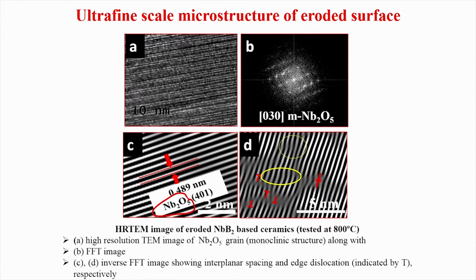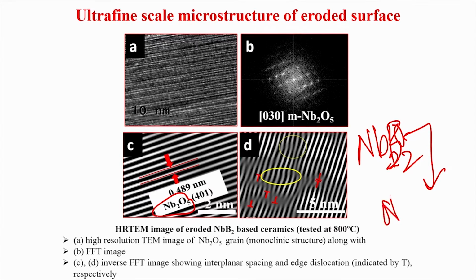Now, this niobium oxide formation is so low that one cannot record it using X-ray diffraction pattern, because their intensity or their amount is much less than what can be detected using X-ray diffraction analysis. But here what we can see is that the selected area diffraction pattern clearly shows that Nb2O5 has formed, and Nb2O5 essentially is the result of niobium boride, NbB2, undergoing oxidation to Nb2O5 during the erosion wear at 800 degree Celsius.